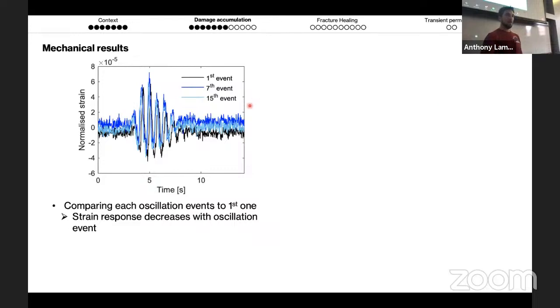Then when I looked at the individual strain events, what we see is that the black one is the first oscillation event that I introduced, and the light blue is the last oscillation event in one test. I've done the comparison for all of the tests, and for all of them, the strain response, as the test progresses, is being reduced compared to the first event. Okay, so the more events you have during those tests, the more the strain response decreases.